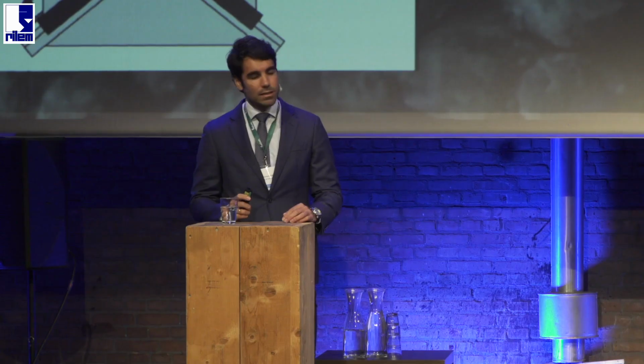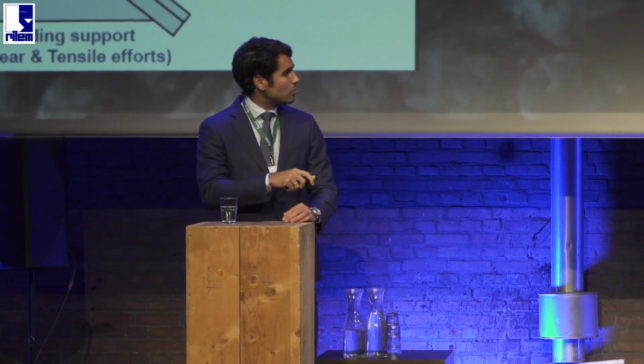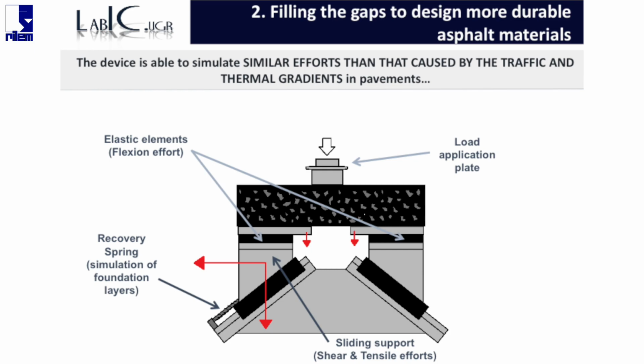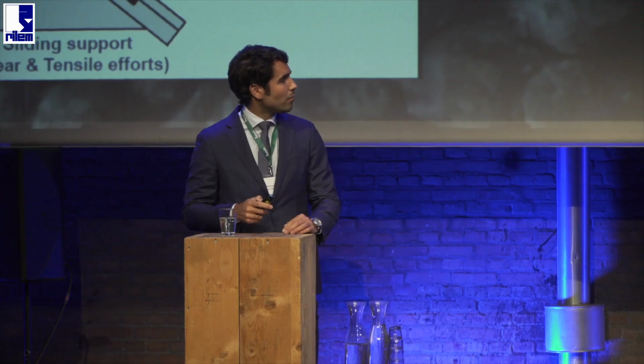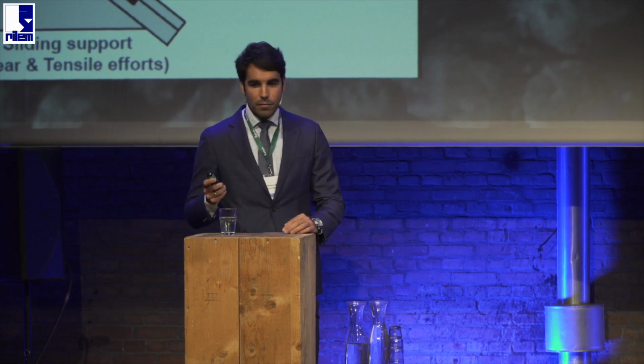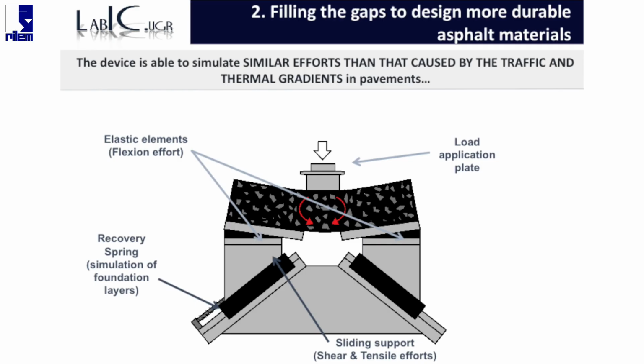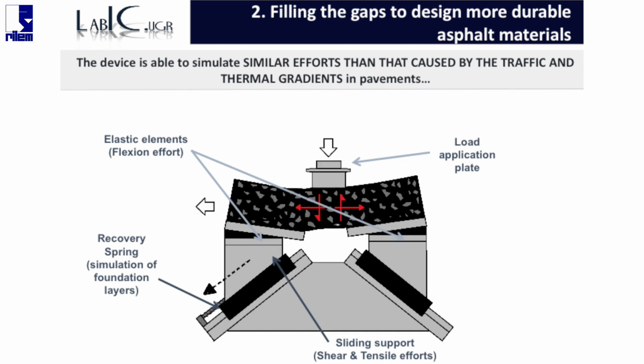For this purpose, this test is composed of a base where two supports are placed, and over those supports there are two places where the specimen is fixed. Under those places there are two elastic elements that, when we apply a load, like a traffic load, allow for the bending of the asphalt material, and after that one of the supports is fixed and the other one can move. So when the bending moment is reached, the sliding support moves, inducing a shear and tensile effort inside the volume of the material that we are evaluating. We have a recovery spring that simulates the foundation layers in the material.